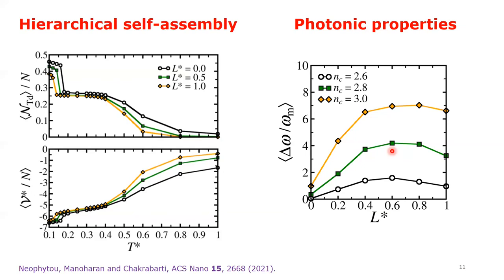Remarkably, the photonic band gap of this segmented rod connected diamond structure is thus found to be robust to stacking faults.